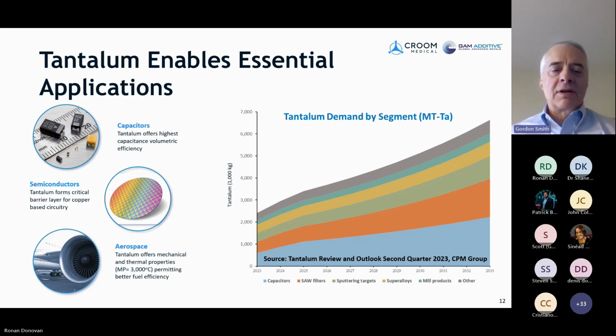It's also interesting to find, if you look at semiconductors, greater than 95% of all semiconductors produced today use tantalum in the stack structure within the circuitry. Tantalum forms a critical barrier layer between the copper circuits and the underlying dielectric layers. So another interesting application is actually in aerospace. Here, to leverage a little bit different property, tantalum has an extremely high melting point, 3000 degrees C. So it offers alloys that can perform at elevated temperatures. This permits then the engine designers to operate engines at higher temperatures, which then increases fuel efficiency for the engine.